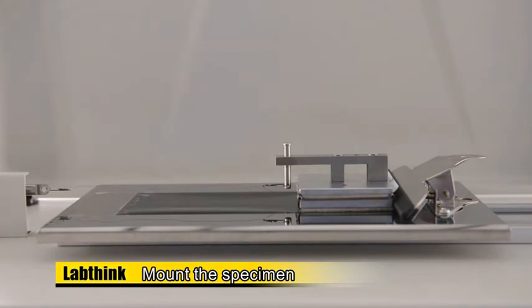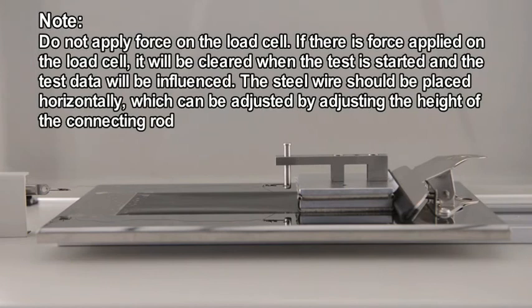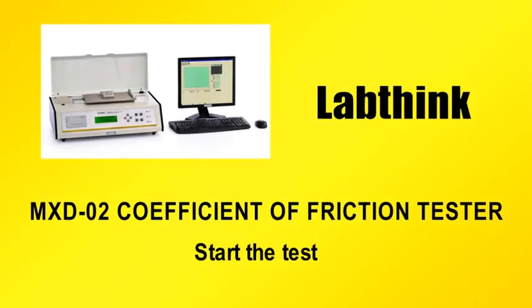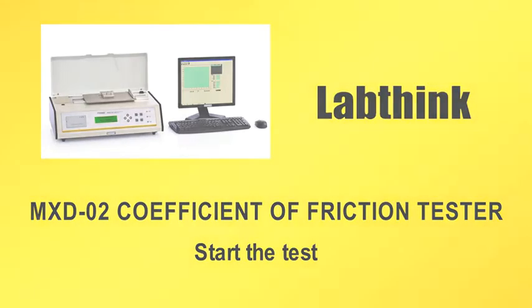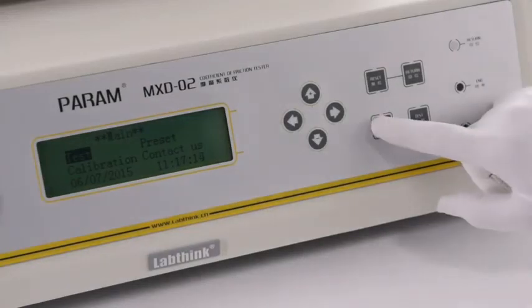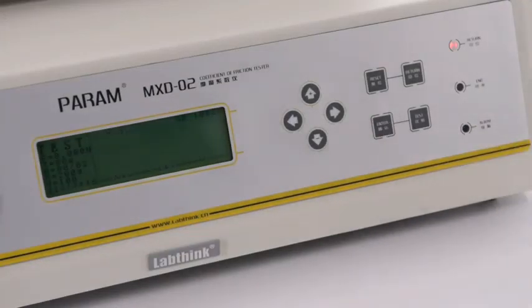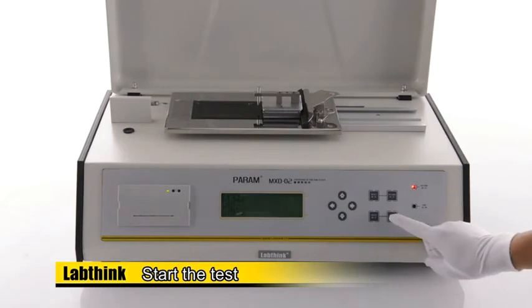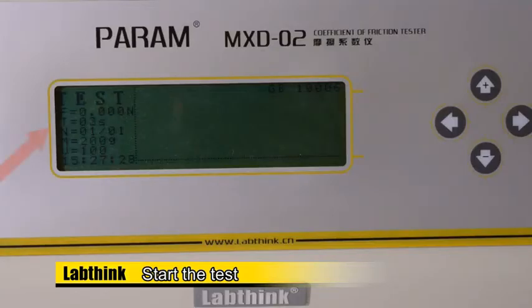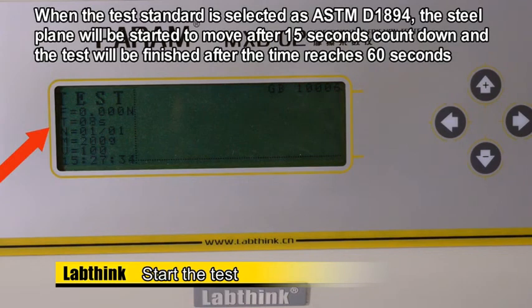Then place the sled with loaded specimen at the center of the plane. Connect the load cell and sled with steel wire, which should be stretched almost straight, slightly loose. Start the test. Press Enter to enter the test interface. Press Test Key and the system starts counting down. 15 seconds later, the steel plane will be moved and the force value will be cleared.